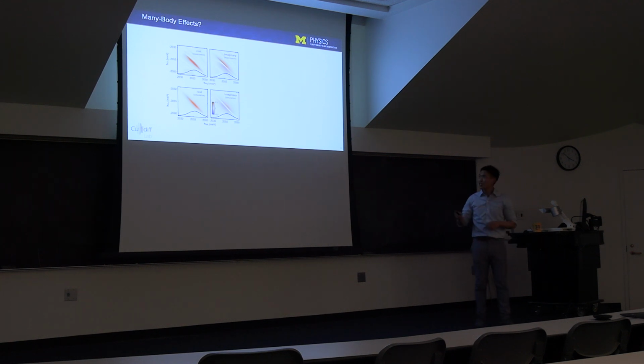Yeah, so just as one last check, we want to see if many-body effects, in particular biexciton resonances, are distorting the pedestal feature that we're trying to characterize. So we do this by phasing our 2D spectra by maximizing the real quadrature and comparing the experimental and simulated quadrature 2D spectra, which I think agree pretty well. And you can see this from the cross-diagonal slices as well, where we don't see any strong biexciton features that would show up as negative peaks in the real quadrature. And you can see this from the phase as well.